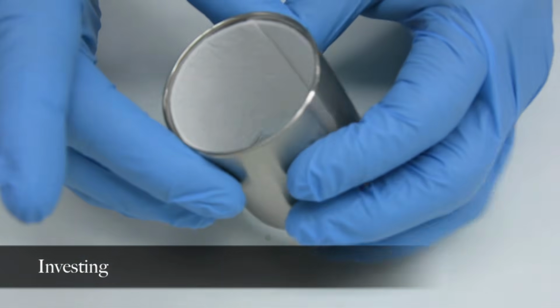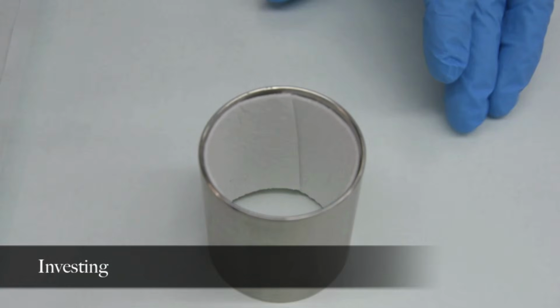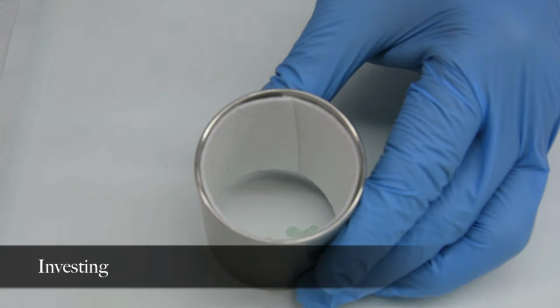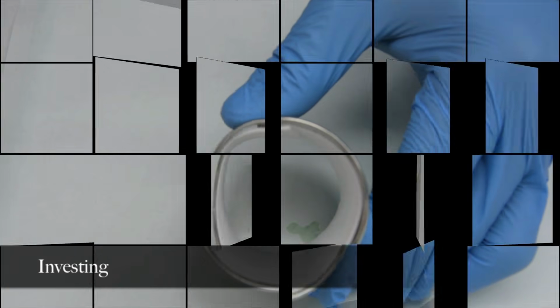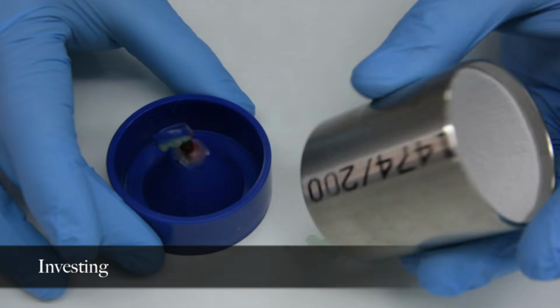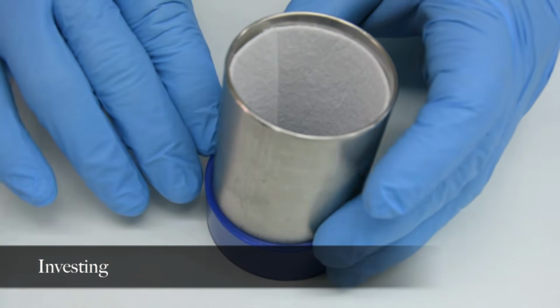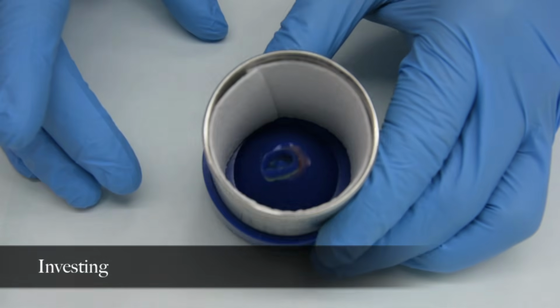A resilient liner made of cellulose paper is placed on the inside of the ring to provide a buffer of pliable material against which the investment can expand, to enlarge the mold in order to compensate for metal shrinkage upon solidification. It also permits easy removal of the investment and casting from the ring after casting. The liner should be 3 mm short of both ends of the ring, so that the investment will be partially supported by direct contact with the ring after the liner has burned out. The ring is rotated firmly onto the crucible former with care taken to avoid snapping movements or contact of the wax pattern with the ring.